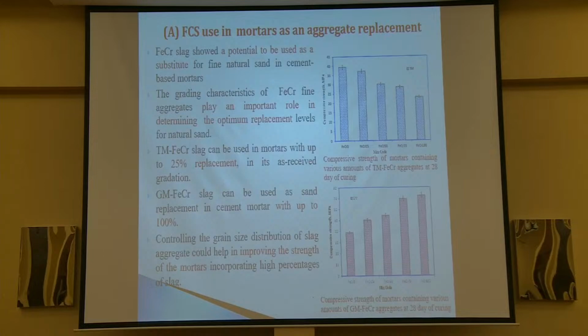And these are the results of our study, in mortars, of course. In the first material, we noticed that when we increase the percentage of the slag, the compressive strength is reduced. This is due to the poor grading of the material, as we used the material as received. And for the other source, we find that there is an improvement in the compressive strength.